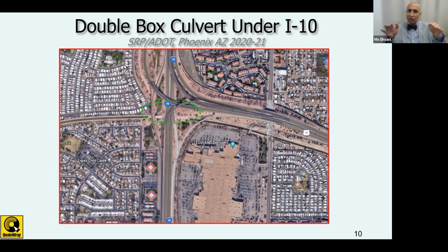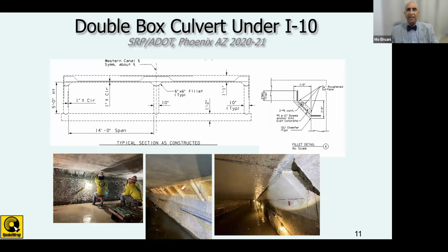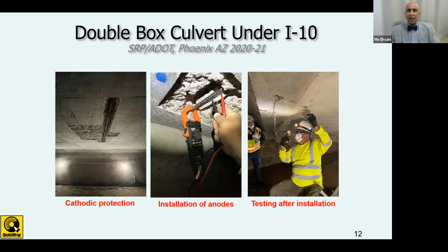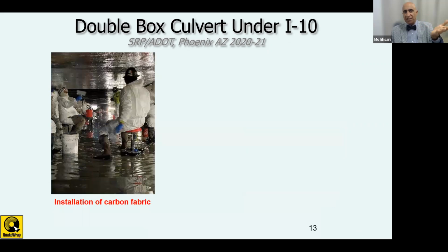The 2 box culverts were corroded at the top. And here, as you can see, the cross section of the box culverts, they're about 14 feet wide. And there was some corrosion at the top that they wanted to repair and strengthen. So the repair included embedding a cathodic protection system for some of the corroded rebar. And then those were patched up. And then on top of that, the fabric was installed.